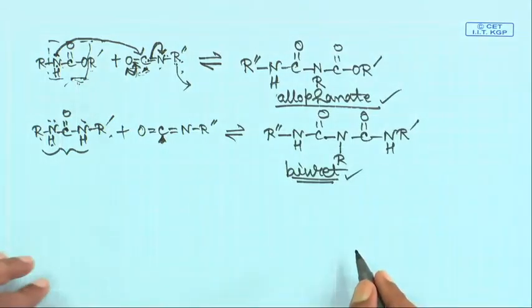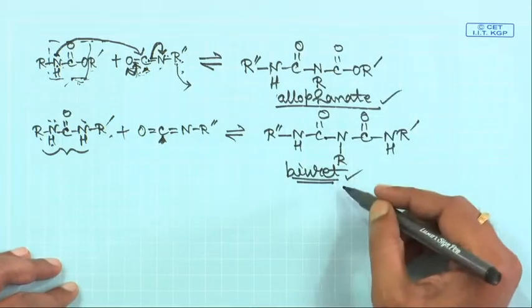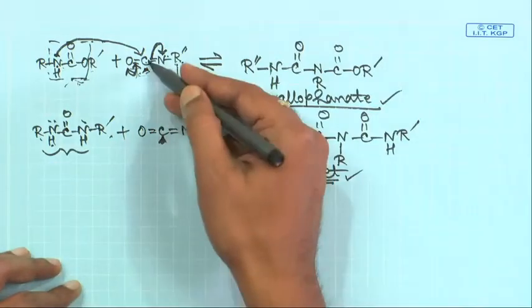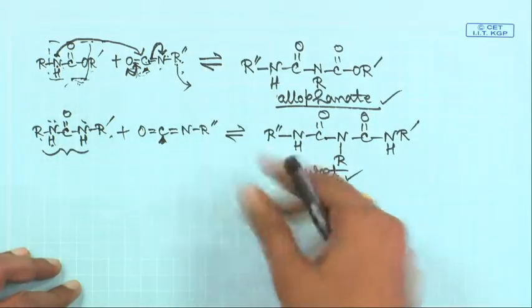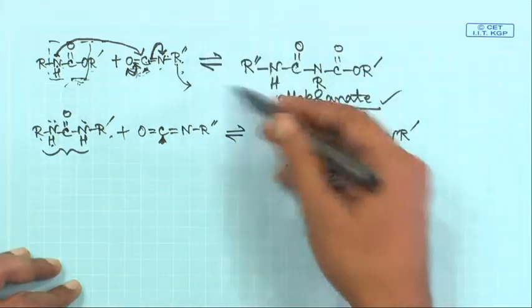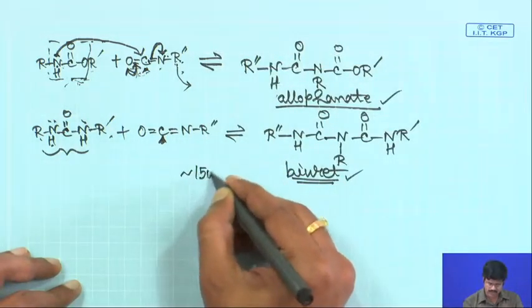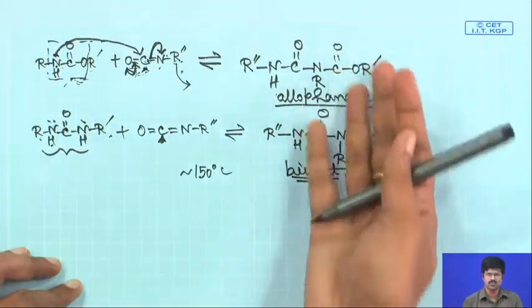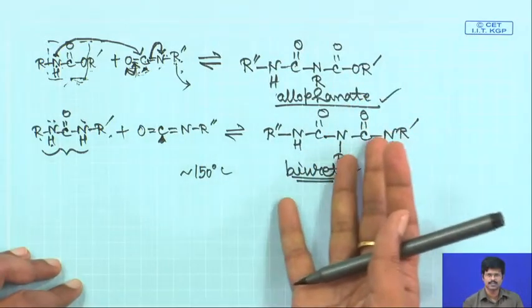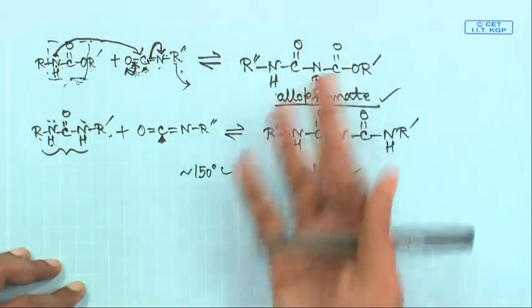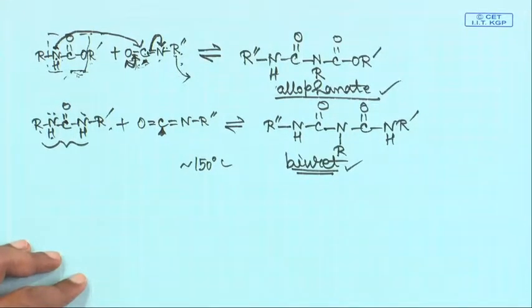This kind of crosslinks will be present in the system when preparing polyurethane polymers, which will contain both urethane and urea linkages. However, these are reversible reactions — if you heat it up to around 150 degrees Celsius, the reaction goes backwards. So even if these crosslinks are produced, that is not detrimental, because at slightly higher temperature the reactions will go backwards and these crosslinks will no longer exist in the system.